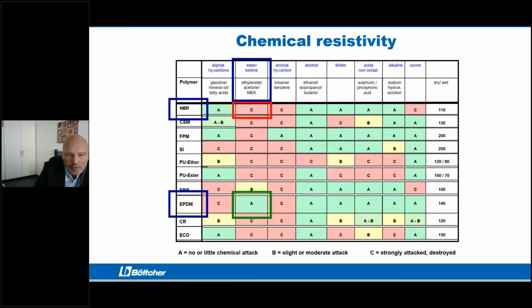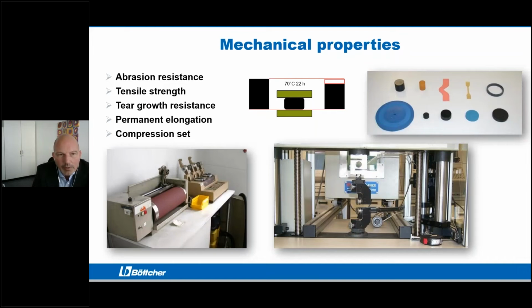So all over this, we checked in our laboratory what will be from the chemical side the best material to have a long life of your roller and/or sleeve covering. We do also in our laboratory some further tests. For example, in case of mechanical properties, we test the abrasion resistance, the tensile strength, the tear growth resistance, and also some other things like compression set. This is all to have as long a lifetime as possible, a long service time. This is also important to have a sustainable and reliable production.